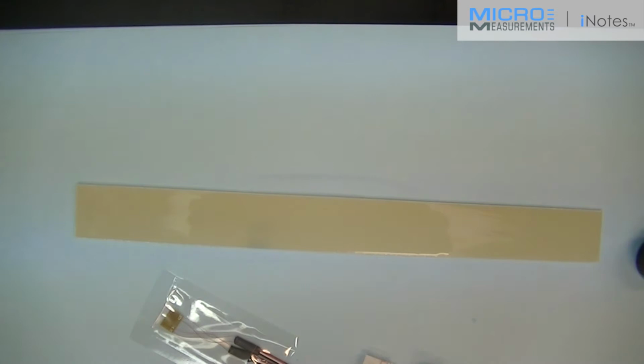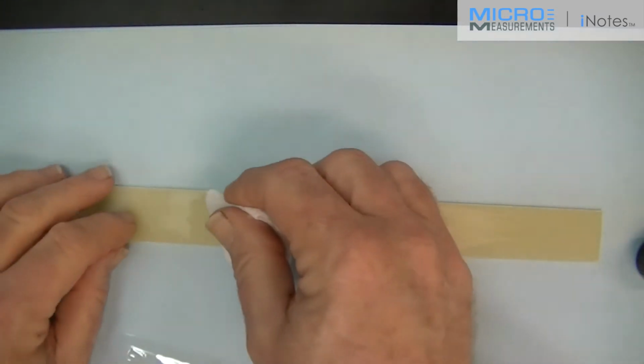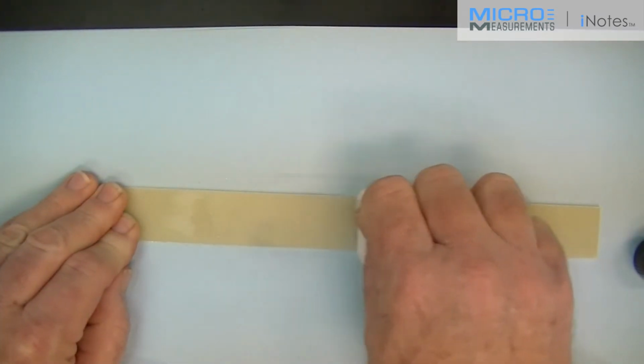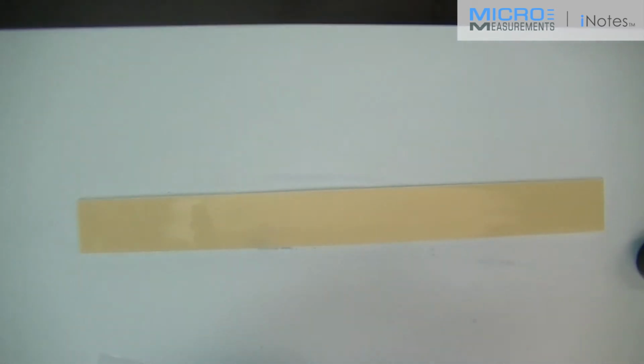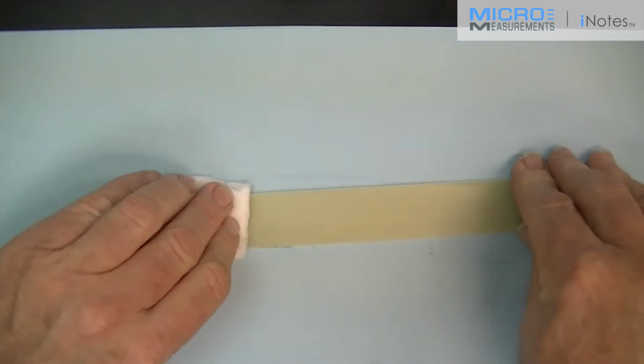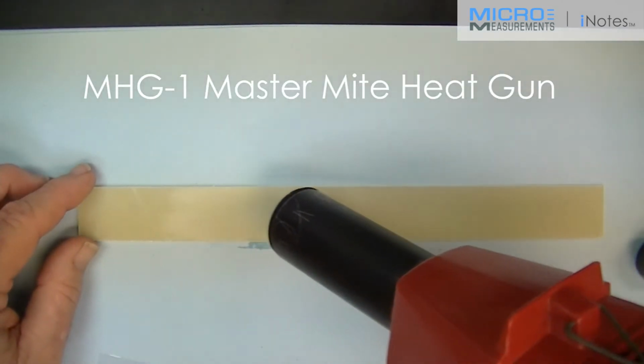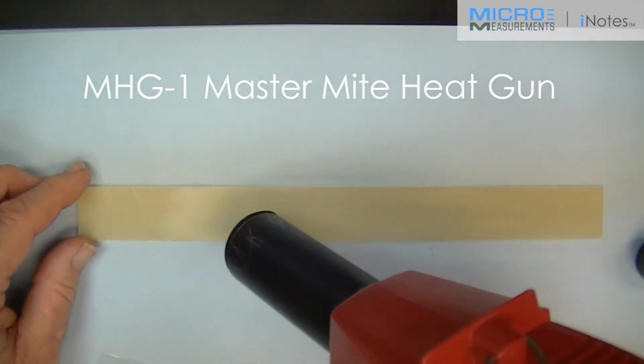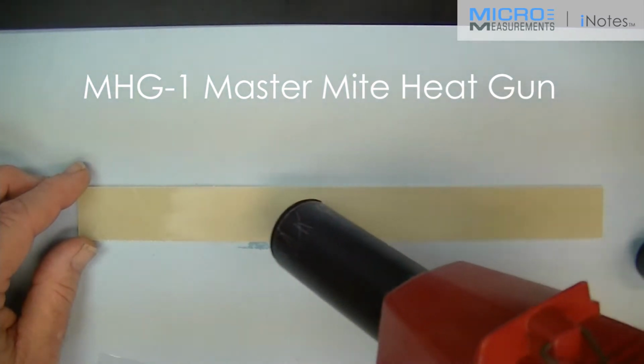I'm now going to take a dry gauze sponge, fold it into quarters, and with a single wiping motion absorb the excess material off the beam. Because this is a composite material and they are fairly hygroscopic, we want to make sure we get rid of all this Neutralizer 5A, so I'm going to use a warm air blower and I'm going to dry the surface of the beam extra.